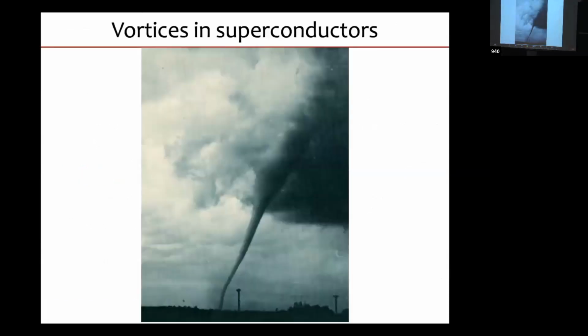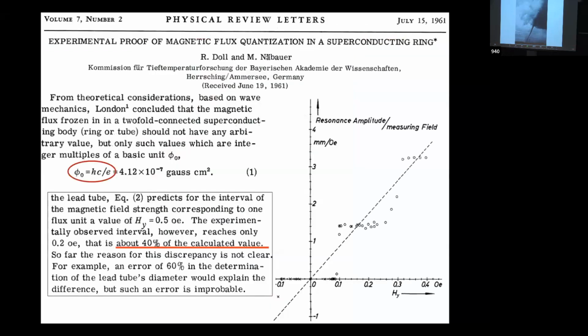Okay, so the way that this shows up in a superconductor is through a vortex. So this is a vortex in a classical fluid. Imagine that you have a vortex in a quantum fluid. It actually can look a lot like this. There's superfluid flow, which gets faster and faster as you get to the center until it becomes so fast that you have a core of the vortex where superconductivity is destroyed and you have normal electrons. The vortex can also wind like this vortex. So there are quite a lot of similarities. But as I said, one of the main differences is that vortices in superconductors are quantized.